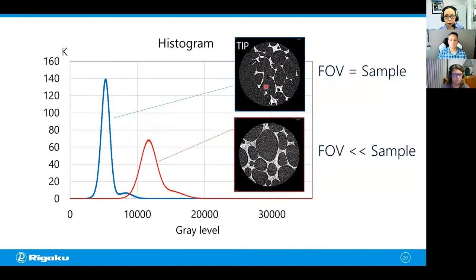So with the tip, when the sample size was more or less matching the field of view, you see a sharp peak, this is a histogram. You see a sharp peak from air and another little peak from the foam, and you have a dip in between, meaning that they have pretty good contrast and are easy to segment. When you look at this larger sample scan, the air peak is broader, and the same for the polymer. You don't see a clear dip or separation between the two. So this means that it might be challenging to segment this image using, at least, traditional thresholding.